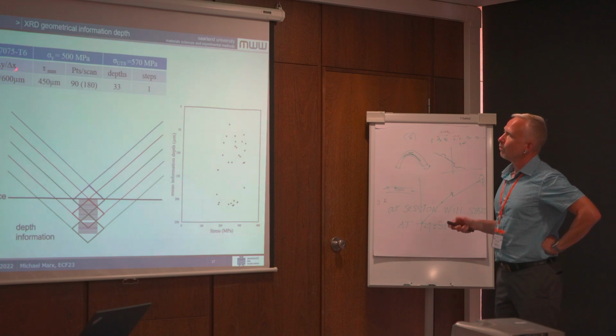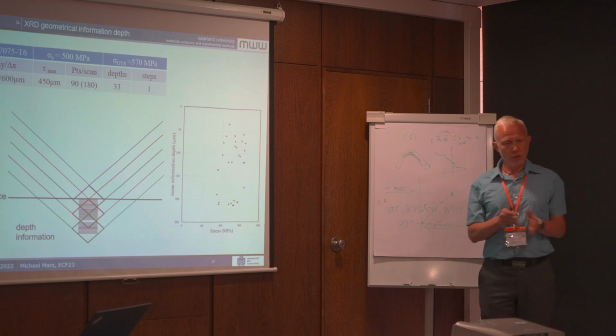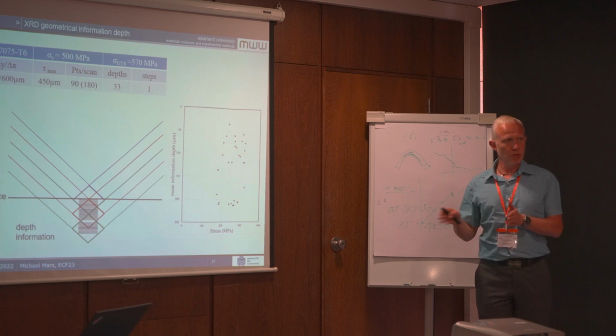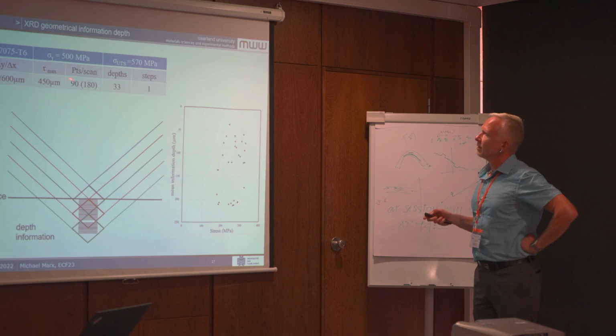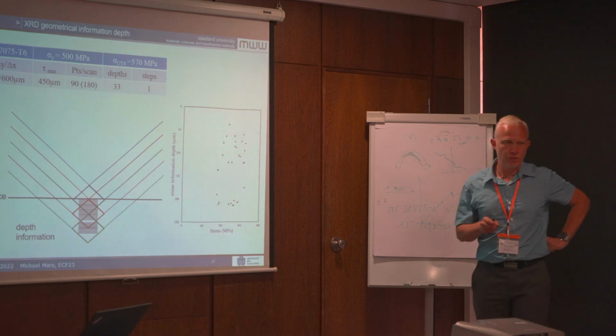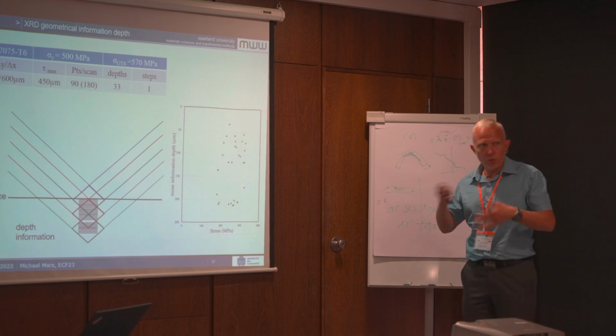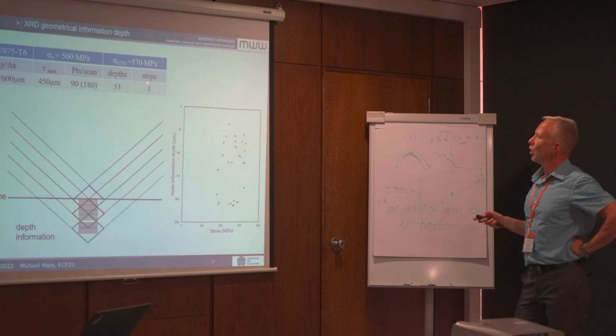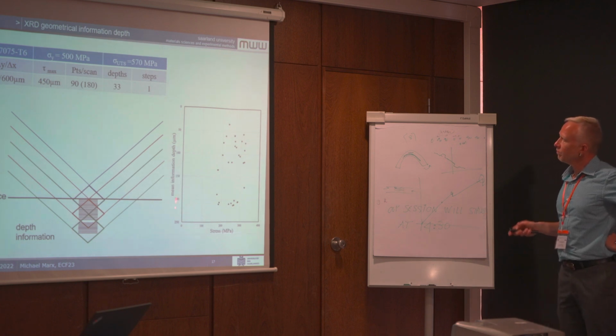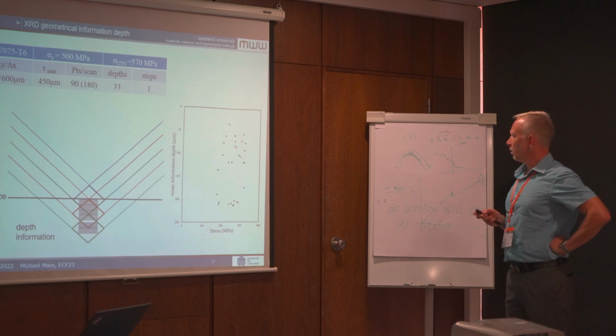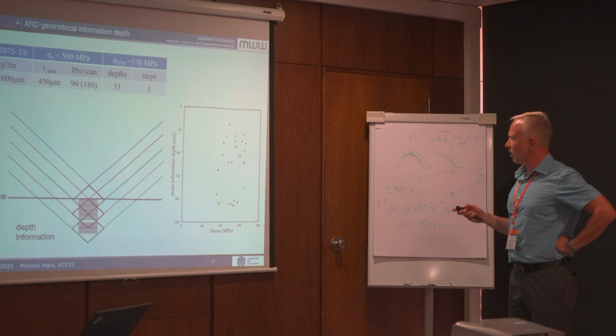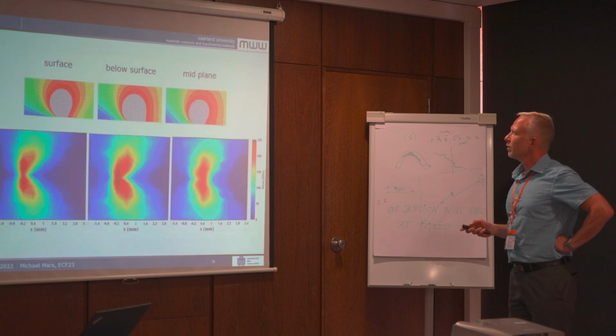Here, this is the totally measured area. We had in total 450 microns, which is the maximum depth we could reach in our aluminum alloy with the X-rays. We had 90 points per scan, 33 different depths, and one step of loading. Because at the beginning it was a fatigue experiment with overload and so on, but in this case we just had one. And what you get here is the stresses for different information depth, and this looks more or less statistical. But if you have a look at the 3D distribution, this looks different.